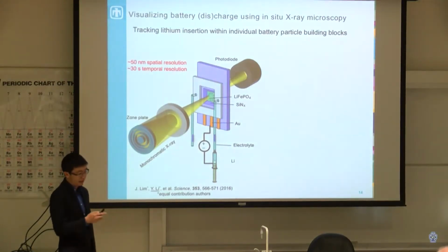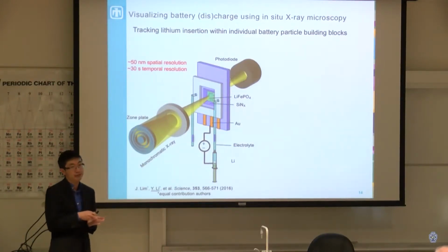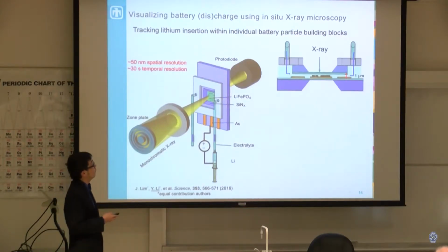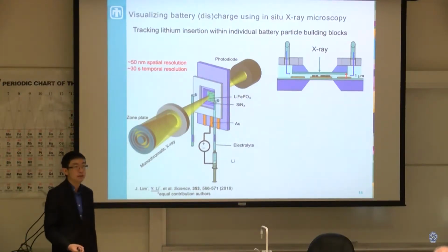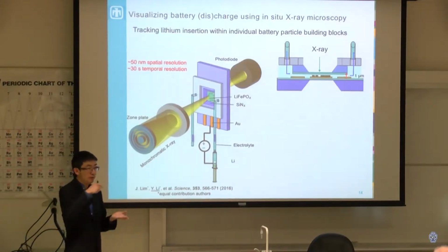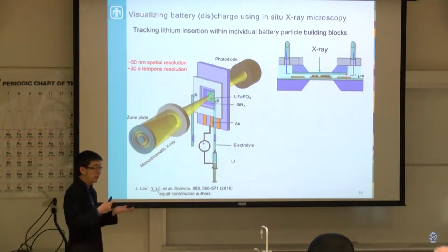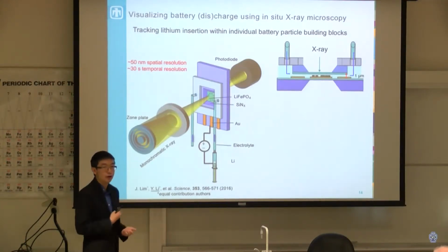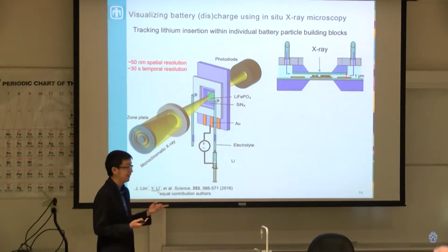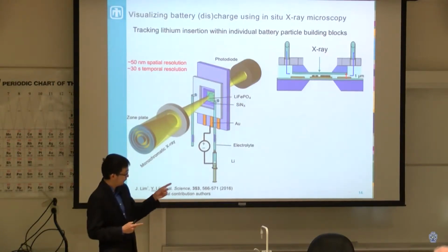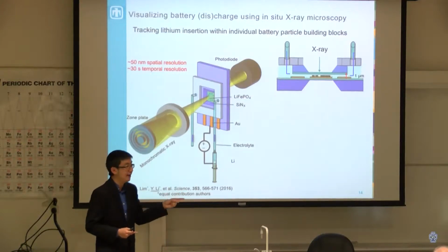These are not just used for interesting pictures and cool videos, but we're also trying to learn something about the mechanism. The process we've done is that we took our battery particles and put them inside a very thin microfluidic liquid cell. If you look at the cross-sectional view, we put our batteries inside this fluid channel that is only 1 micrometer thick. The reason it's 1 micrometer is because the X-rays used are very low energy, so they can only penetrate through a very thin slice of material. If you look at the manual, they tell you basically how much time you can put your finger inside the X-ray beam before you die.